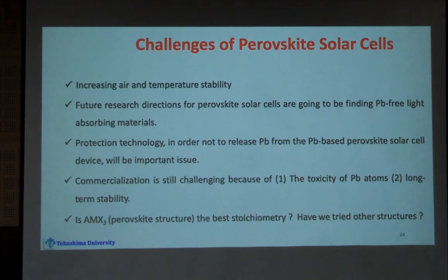It cannot show good stability at higher temperatures like 80 degrees, 100 degrees. When light energy is coming, the solar cell temperature is more than 100. Outside, even though it is 40 or 45 degrees, if you check the temperature at the solar cell, it is more than 100.